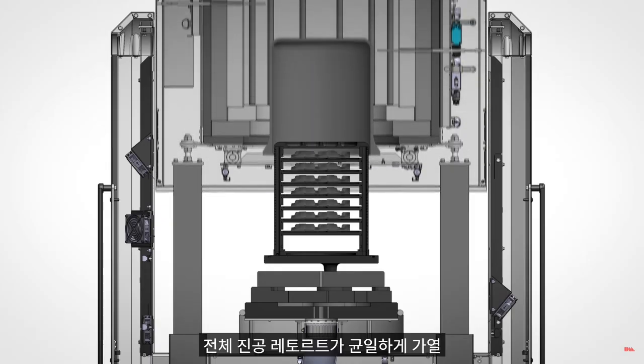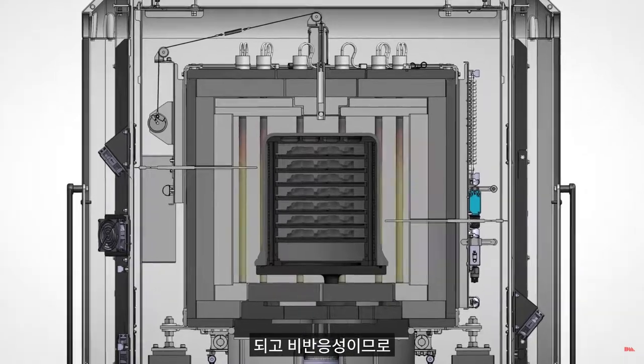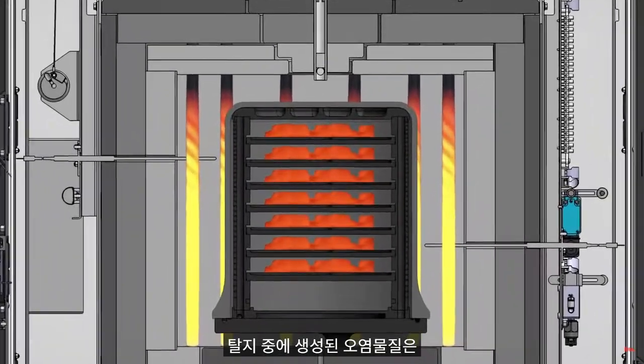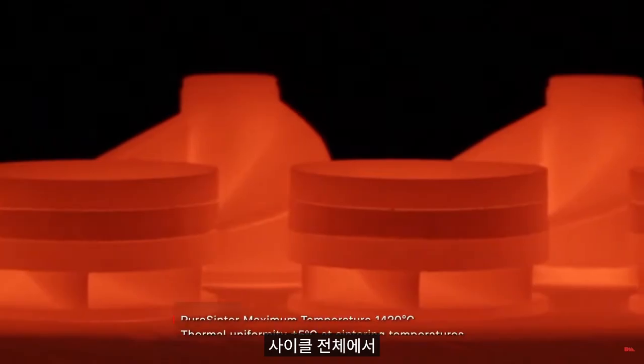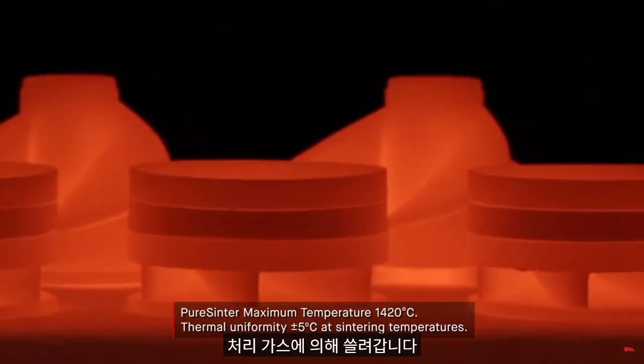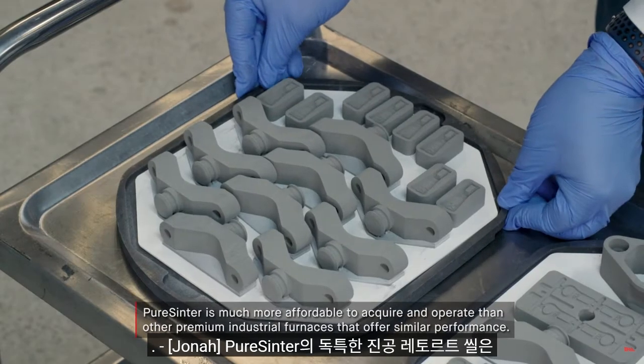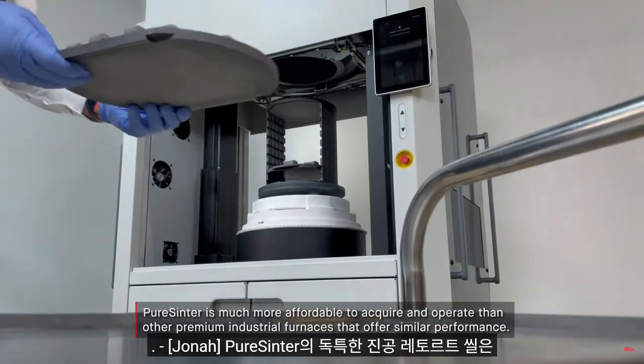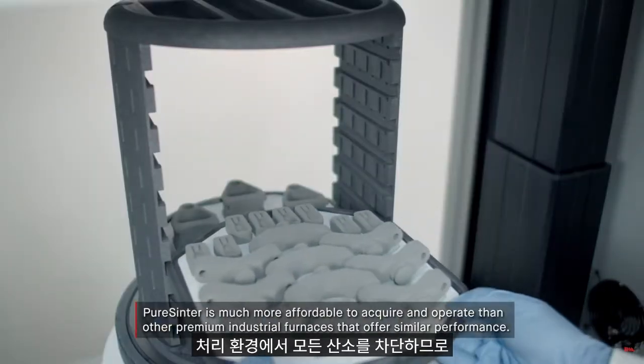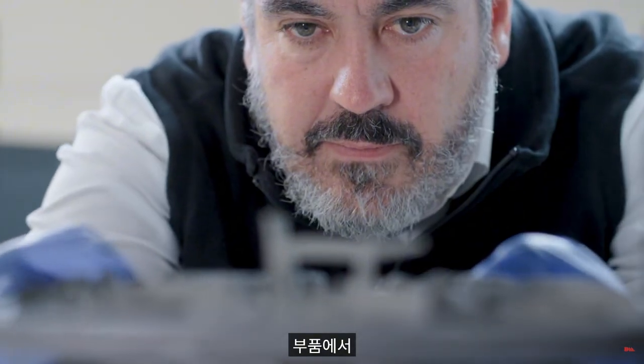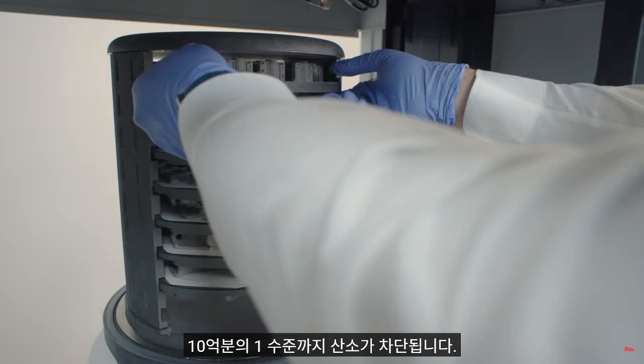Since the entire vacuum retort heats uniformly and is non-reactive, contaminants generated during debinding have nowhere to condense and are swept away by the processing gas throughout the cycle. PureSinter's unique vacuum retort seal keeps all oxygen out of the processing environment and therefore out of your parts, down to the parts per billion.